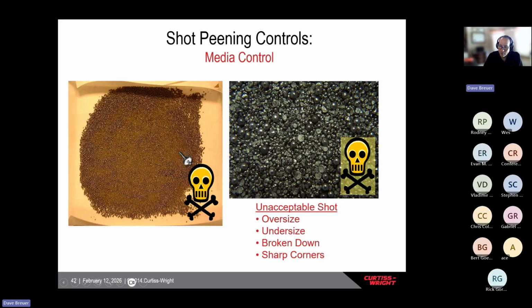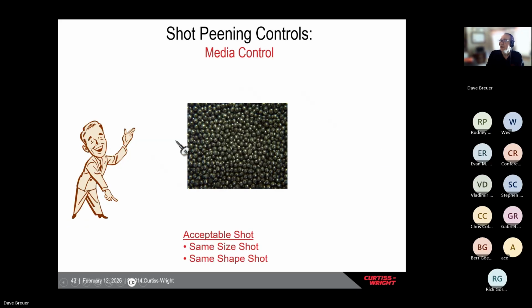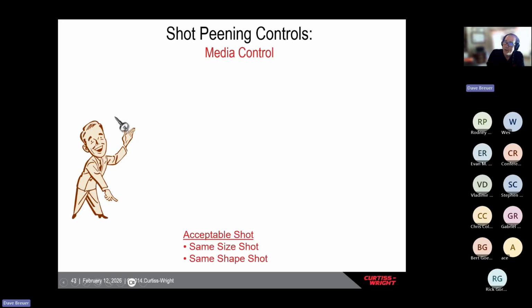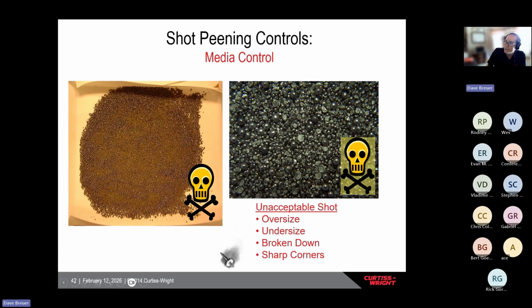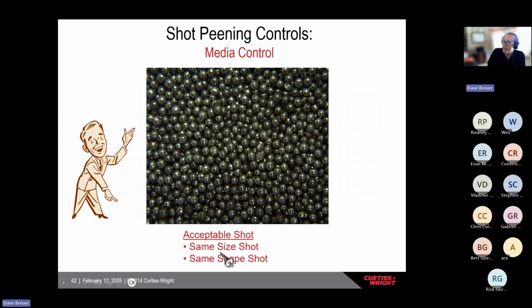What we do is every 8 hours, according to the mil spec, the shot has to be inspected. If there's a certain percentage of broken down or undersized media, that shot has to come out of the machine and go through the classifier to remove the undersized and broken down media. This is exactly how you do not want your shot to look, and this is exactly how you want it to look.